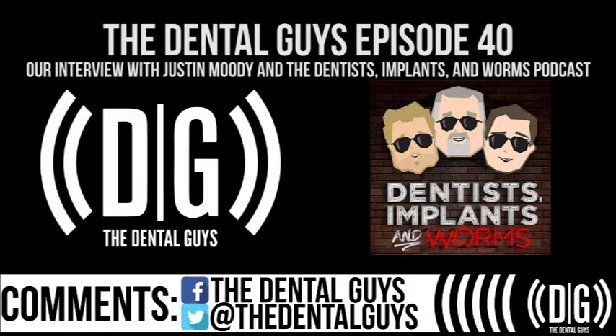For me, even though I know what you're saying, I always do verified, because with zirconia, I'm worried. I like zirconia, but I'm always worried that if something is off, the zirconia is going to be the place that I'm going to see the problem catastrophically, versus cement, which would break on the cylinder before the zirconia. I know, but to me that's a big deal.